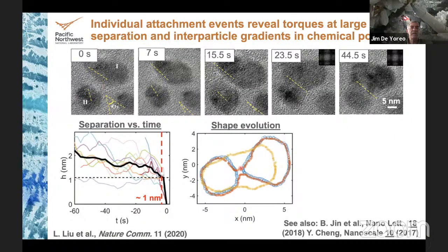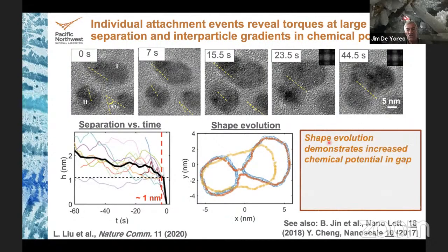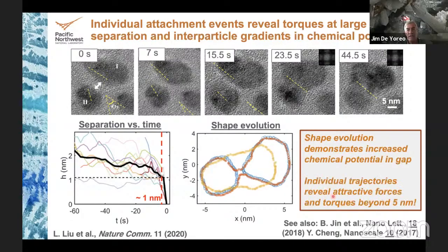Now this solution is at equilibrium. We're not growing particles, but that implies that we're getting growth in this region, even though the solution is at equilibrium. And the suggestion then is that the chemical potential is somehow different with respect to zinc oxide in the gap than it is out in the bulk solution. So these are important observations: shape evolution demonstrates an increased chemical potential in the gap, and the individual trajectories reveal attractive forces and torques beyond 5 nanometers.